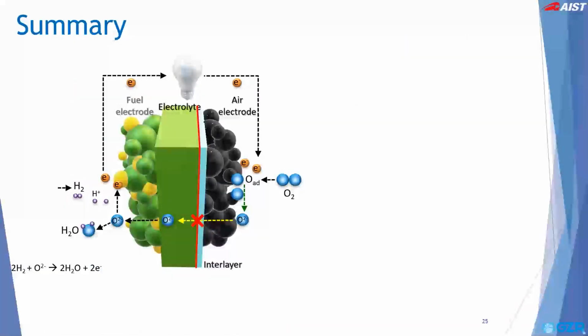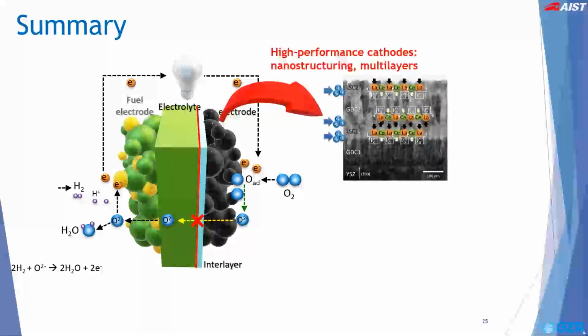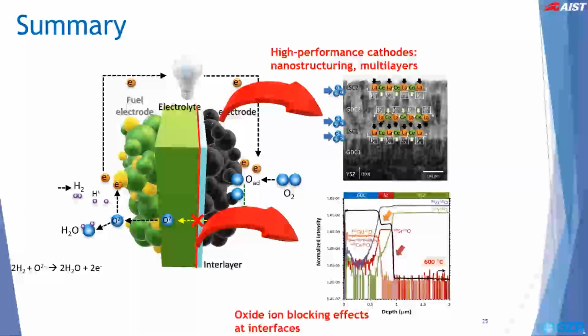To summarize, in this presentation, I have discussed 3 specific topics concerning the development of materials for SOFCs. The first topic is on nanostructured and multilayered cathodes, exhibiting superior surface exchange rates compared to conventional materials. The second is on the oxide blocking effects due to the strontium zirconate formation. Using the model structures and employing the SIMS isotope labeling technique, we were able to confirm the role of the strontium zirconate layer on oxide ion transport across such interfaces. The important finding is that it is not the strontium zirconate layer per se that blocks ionic flow, but the nature of the interfaces with this phase.